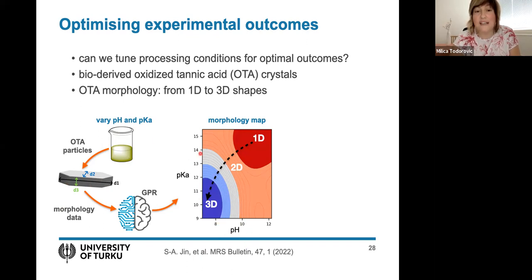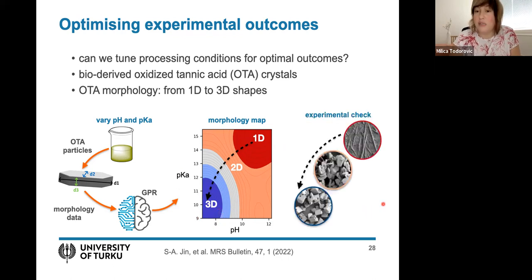So you can see pH on the x-axis and pKa on the y-axis. And what the model predicted is that if you have a high pH pKa environment in the solution, you would make 1D tannic acid particles. And if it's a milder environment, low pH pKa, you would get 3D particles. And then indeed, when we looked at the samples again, we found that all of the 1D samples were in this region. And then the 3D samples is exactly how this looks. And then in the middle, you could find all kinds of variations, sometimes a platelet and sometimes really short matchstick 1D particles. So this was a really useful outcome, even though this is not a very sophisticated use of Gaussian process regression and surrogate models.